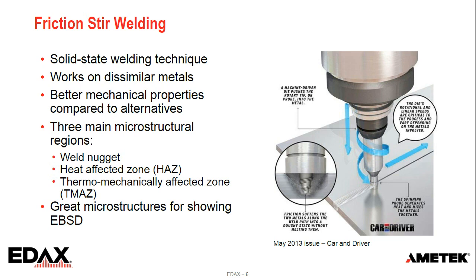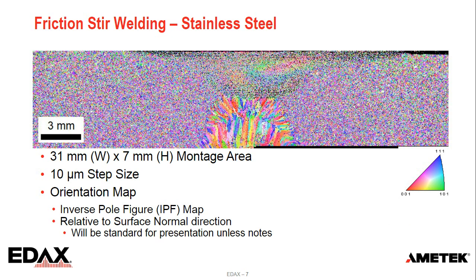So this is an example from a friction stir weld. This is a stainless steel alloy. This is using what we call a montage scan. So it's covering a large area, 31 millimeters by 7 millimeters. And basically, we take a field of view, we collect the data, we move the stage, we take another field of view, we repeat that, and when we're done, we stitch them all together to see the microstructure. So this is looking at an area with a 10 micron step size. The map I'm showing here is what we call an orientation map. This is where the colors correspond to the orientation, in this case coming out of the surface normal direction. That will be the standard direction we use in the presentation, unless I note otherwise.